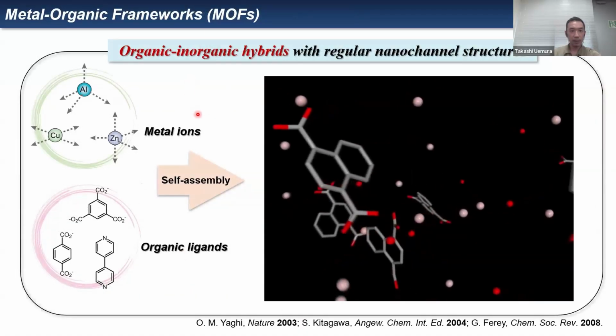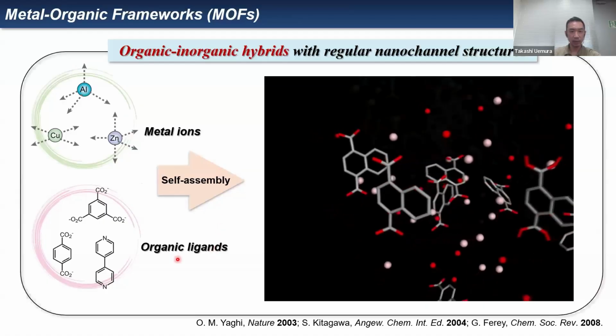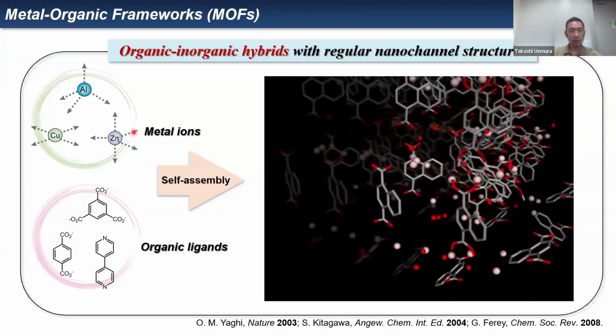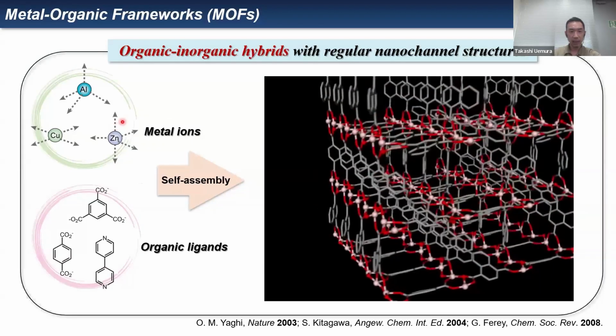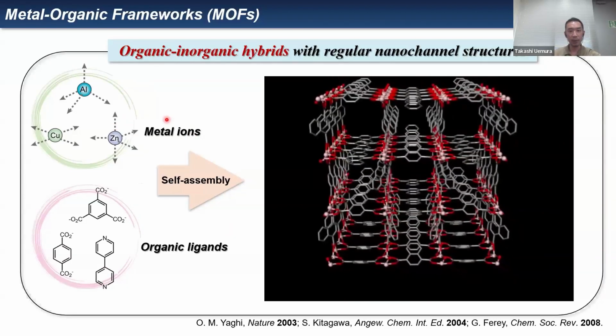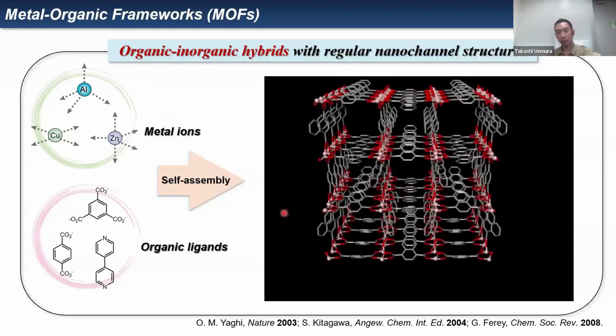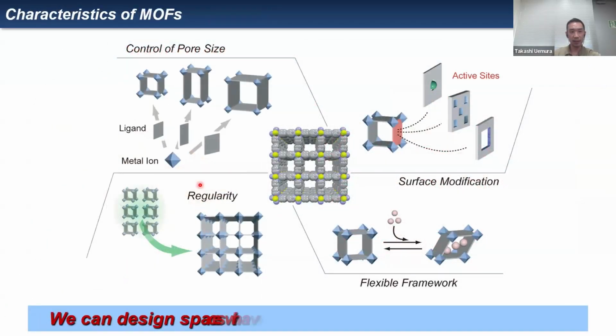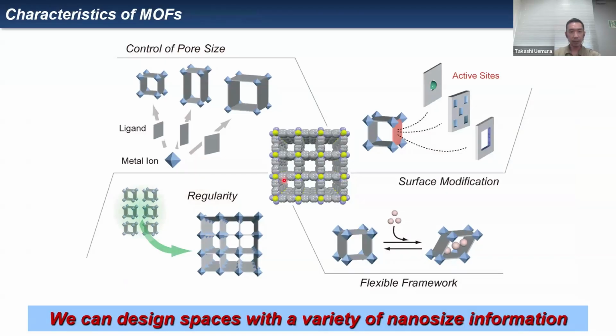Here we focus on metal-organic frameworks, MOFs, which are prepared by self-assembly of metal ions and organic ligands like this. And as you know, these porous materials, MOFs, are usually applied to gas storage and separation materials. Here you can see the characteristics, features of the MOFs. Different from zeolite and activated carbon, it's rather easy to control the pore size or shape by changing the combination of these two components.